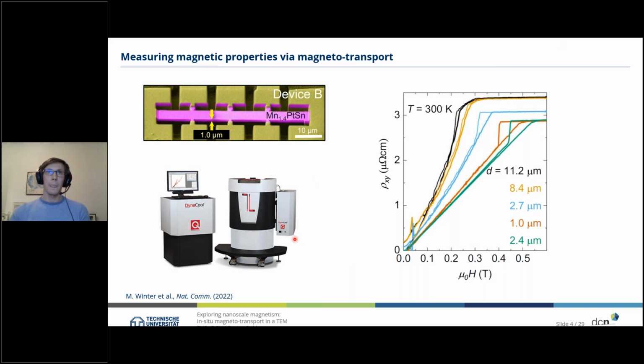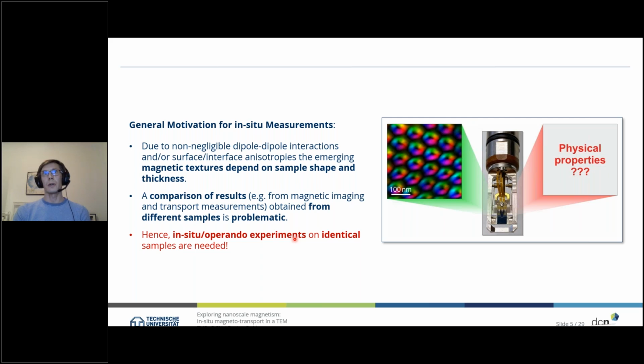And that brought us to the motivation of our research here, of designing such a new in situ magneto-transport measurement platform. We have magnetic textures, which strongly depend on the sample shape and the thickness due to non-negligible dipole-dipole interactions or surface interface anisotropies. And if we now image them in the TEM and compare them to magneto-transport measurements, for example, these measurements are then done on different samples.